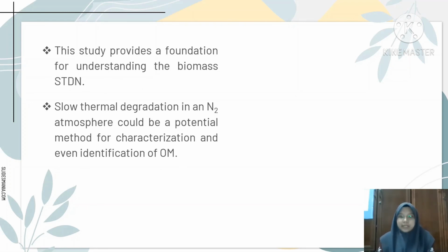Based on all experimental findings, STDN of plant biomass could be divided into three stages. Peak F2 represents endothermic primary degradation processes that occur at a relatively slow rate. This was followed by peak F3, reflecting a transitional stage in which energy was still being absorbed, while the Fx peak represents severe exothermic activity and rapid loss of mass. This study provides a foundation for understanding the biomass STDN. Results reveal that several thermal behaviors overlap, making it difficult to identify components in organic matter. Slow thermal degradation in an N2 atmosphere could be a potential method for characterization and even identification of organic matter.